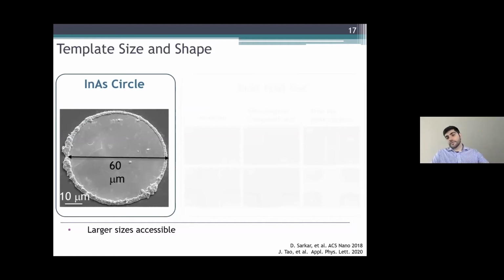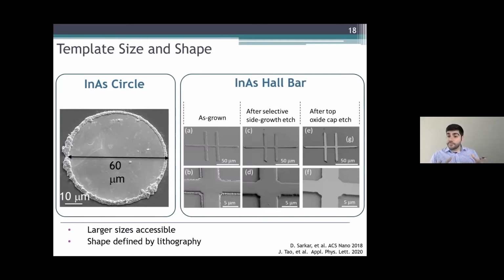So for example, here I'm showing indium arsenide, and I'm showing a 60 micron circle of indium arsenide. You can also pattern it such that you get more complex geometries. Here I'm showing an indium arsenide Hall bar. So basically what happens is you pattern the desired geometry, and then you just do a phase transformation to turn that pattern into your single crystalline domain.